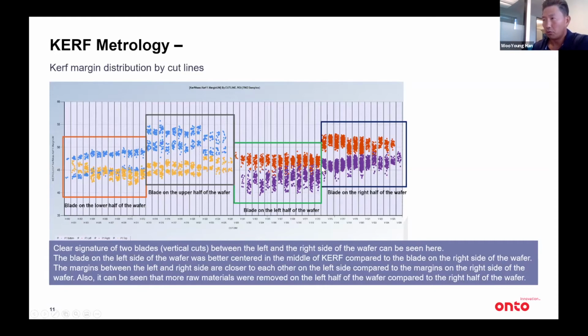Okay, so what do we see here? What can we learn from these graphs? So the first one, let's look at the margin. On the left half of the wafer, the margins are actually closer, right, compared to the right half of the wafer? So this is indicating the position is actually better. Meaning, the ideal case would be these two being identical, like the red and the purple signature, if they are overlapping, that means they are pretty close to each other. That would be the ideal case. And when it's non-ideal, the difference between the two will be larger, indicating the blades didn't go through the center of dies, right?